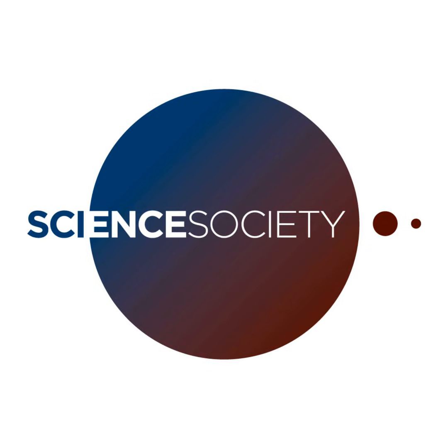That's a very good question. For photovoltaic, since you're asking this question, I would think you are definitely an expert in photovoltaic. I have had some research experience on photovoltaic. Right now, the most used photovoltaic material is silicon. As you know, silicon has an issue. One thing is the band gap. Silicon band gap is only 1.1 eV. With 1.1 eV, the solar spectrum has the UV part that will generate so-called hot electrons. And when temperature goes up, the silicon band gap further decreases, so the hot electron is not good for silicon.